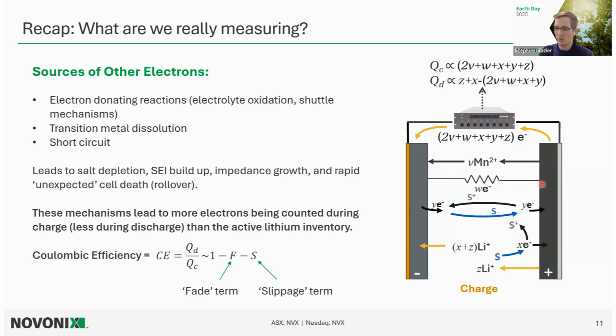If there's a short circuit within our cell, we've just basically made an electron shuttle through the cell. As we're charging it, we're just pumping in extra electrons that we're fighting to charge up this cell. If there's a reversible redox reaction here, which I'm showing, there's actually some interesting papers by Michael Metzger and Jeff Dahn's group at Dalhousie talking about the use of PET tape in cells that eventually cause this type of reversible redox mechanism, which basically acts as this self-discharge and just shuttles electrons through the cell. And you're always counting these excess electrons through your cycler. And then even some irreversible mechanisms like electrolyte oxidation here, you're consuming irreversibly electrolyte species, and you're just donating the electrons to your cathode. And in order to create charge balance, you count those electrons too.